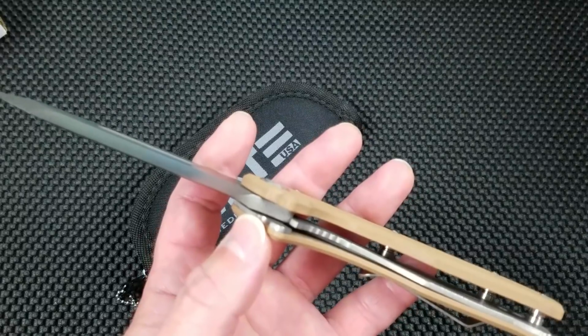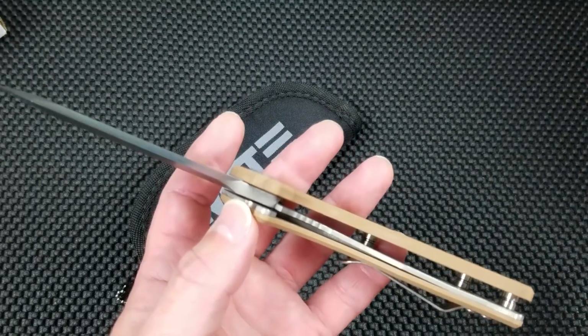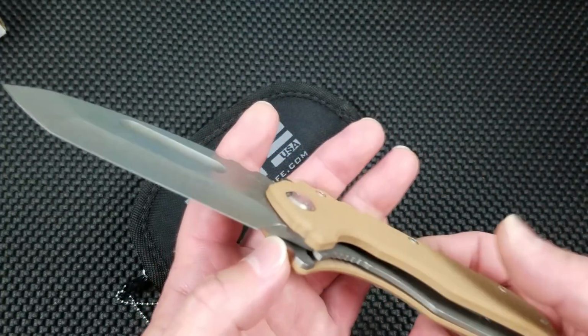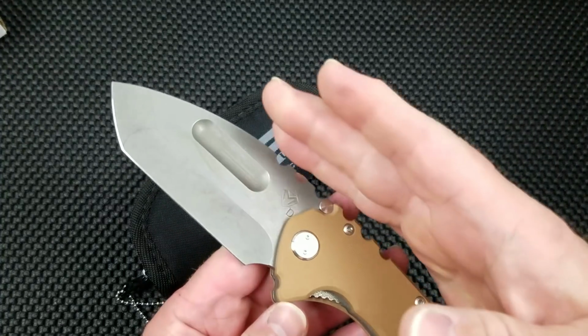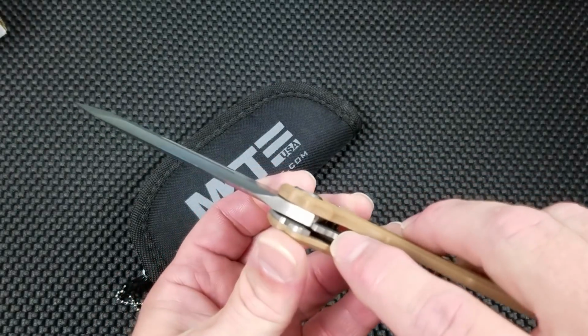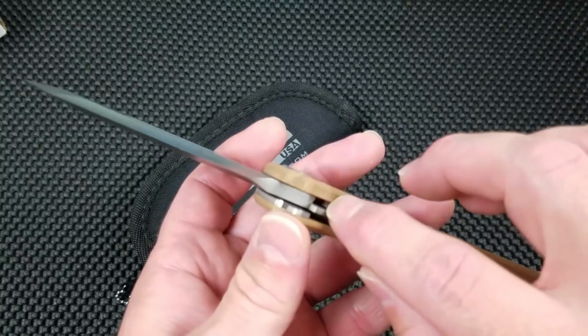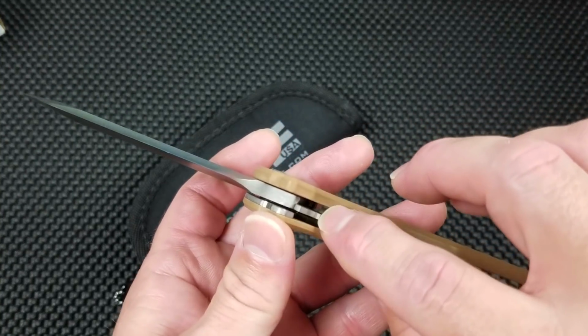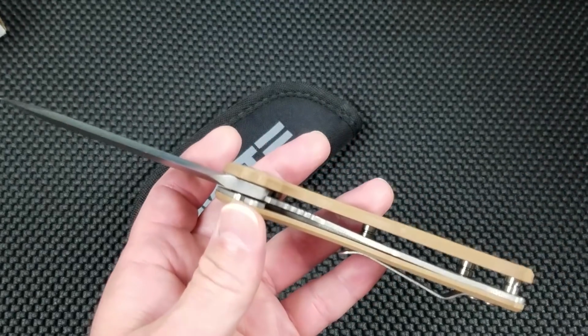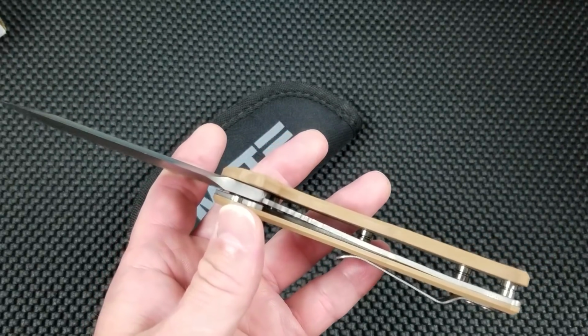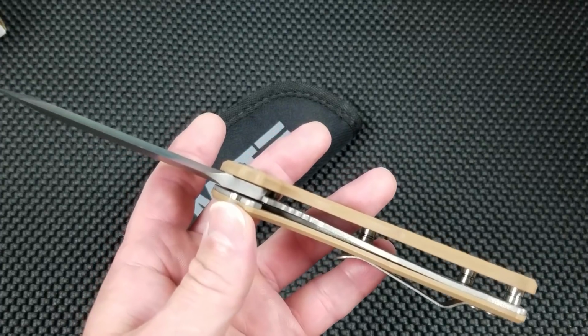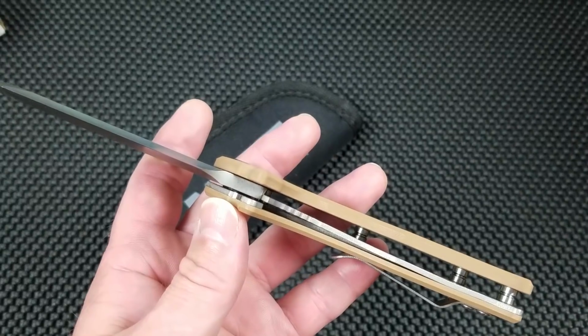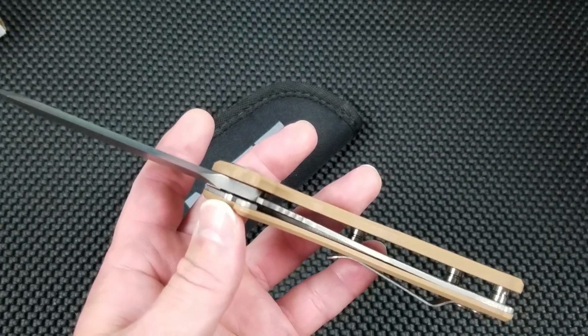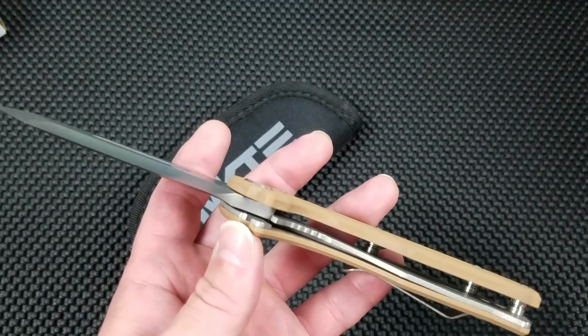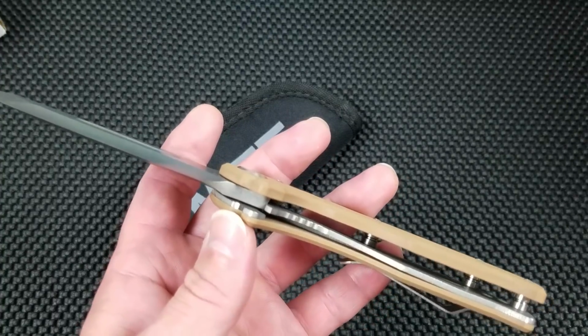Titanium will deform, it will compress under impact with a harder material. There is nothing you can do about that unless you're going to use a hardened lock face insert. And what I mean by that is you see these guys testing knives and they go out and they do some spine whacks on a table or a log or whatever, and they are putting the opposing pressure for the blade onto the lock face. In this case, and with any knife that uses unprotected titanium against steel, that can cause a deformation, a compression of that titanium. There is no way around that. It doesn't matter how much you pay for your knife or who makes the knife. They cannot change that. It is a proven issue in the knife manufacturing world. That is why you see everyone going to hardened steel lock face inserts. It stops the wear issues and the deformation issues.